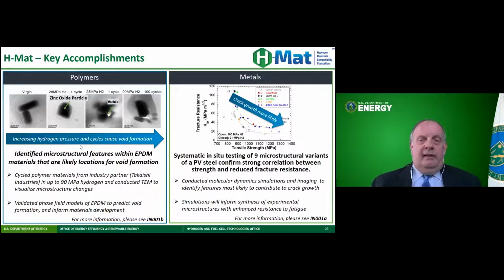Ideally, they work with the actual producers and the actual materials and products used in the infrastructure. So for instance, on the polymer side, they look at various materials that usually include plasticizers or fillers, and then look at what happens when you start cycling them in hydrogen service. In this case, they look at these filler particles, where when you start cycling and putting in the hydrogen, you start seeing the formation of voids. Working with real products from vendors, they're able to identify the mechanisms that lead to the failures. Then by computationally modeling it, they can look at strategies to help mitigate those failure modes. They've been able to iterate in this process with actual producers of elastomer seal materials, for instance, and improve the materials so we get better service.